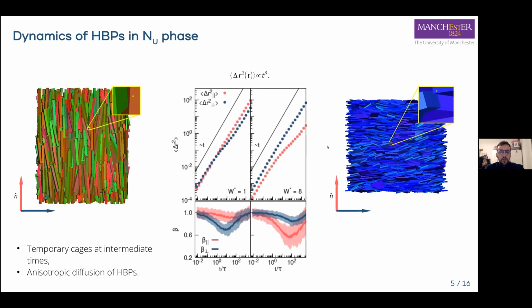And we computed the mean square displacement of the cuboids in the nematic phases, decomposing the mean square displacement in the direction parallel, shown here with red points and lines, and perpendicular to the nematic director, shown here in blue lines and data. We computed the mean square displacement, and by performing the logarithmic derivative of the mean square displacement, we estimated the apparent exponent, so how the mean square displacement deviates from linearity with respect to time.